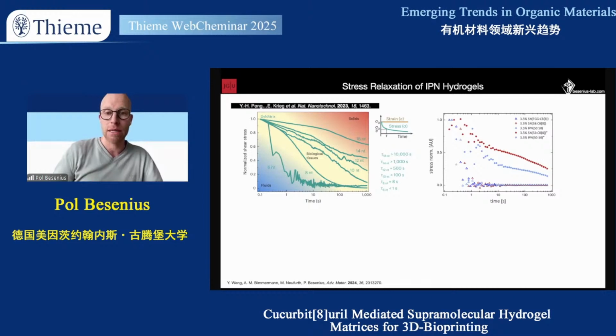And this is now something that we can mimic with these very simple FGG and stilbazolium units, where about 50% is physically cross-linked, so it's pure supramolecular in nature, very dynamic. Still the same FGG remains dynamic. You have a bond dynamic of about 100 milliseconds as lifetime. And the other 50% are permanently cross-linked via the photochemistry of the stilbazolium. So what you start to see is that before you hit it with light, before you fixate that material, super fast relaxation, below a second, which is too fast essentially to print, because you don't have shape stability. And if you hit this with light, you move to the upper right corner. So it's still a dynamic material, but that has some solid contribution and makes it printable.